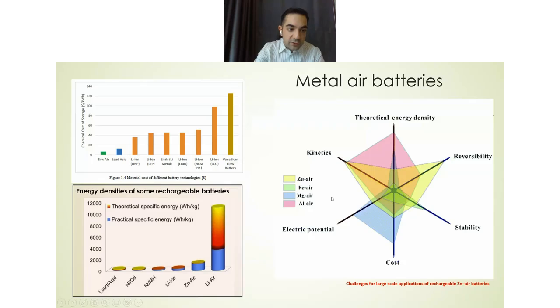Also, when you look at the left down graph, it shows that zinc air battery has higher energy density compared to lithium ion, nickel cadmium, lead acid, and many other types of batteries. And from the graph on the right, you can compare the different aspects of zinc air battery to iron air, magnesium air, and aluminum air batteries. You can see that in all aspects, it is fairly acceptable and comparable. For example, in terms of electric potential, maybe it is not very comparable to magnesium air, but in terms of kinetics and reversibility, it is higher than the other candidates.